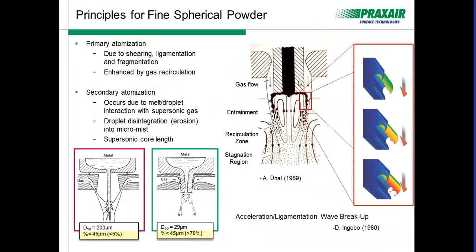So as we feed the liquid through this nozzle, that liquid, as I move down to these figures below, is either going to free fall a given distance and then interact with the gas structure. In doing so, the gas loses a lot of its momentum, and therefore has less velocity when it strikes the liquid. You can think of it as the energy transfer is cut down by about an order of magnitude, and this process creates large droplets. So the only process taken advantage of here is really primary atomization, but very little, if any, secondary atomization. And that's where you make your fine powders. The powders that are less than 45 microns in diameter are, again, 325 mesh.